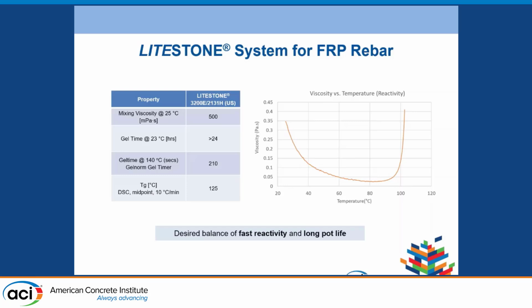Here I also show the viscosity versus temperature profile. Basically, initially before 80 degrees C, with the temperature increase, the viscosity will drop, which is good for the fiber impregnation. And then once you reach 90 to 100 C, the viscosity will increase very fast, showing the fast reactivity. So this system shows the design balance of fast reactivity and long pot life.